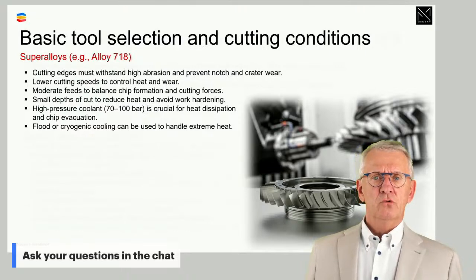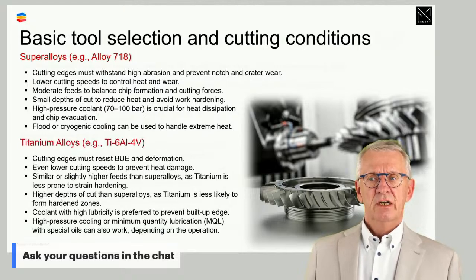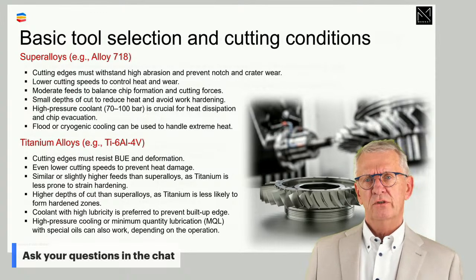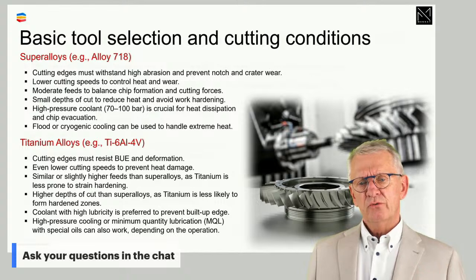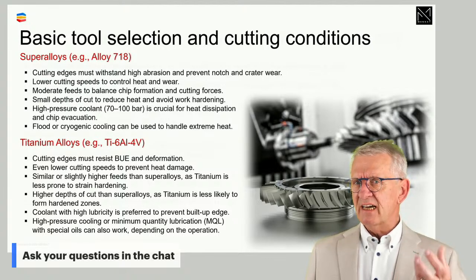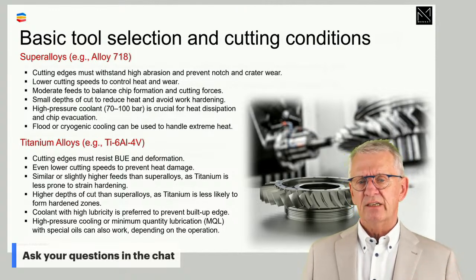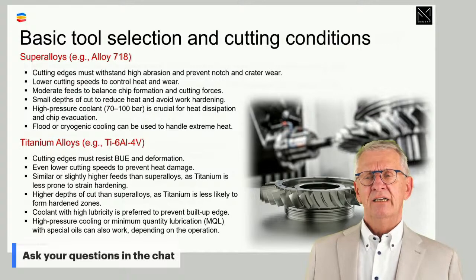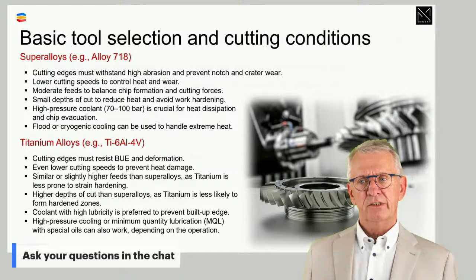When we talk about tool selection, superalloys, we listed the things about tool selection. Titanium is different. Cutting edges in superalloys, they have to have abrasion resistance, notch wear resistance, crater wear resistance. That is important. Where in titanium, it's more about the chemical reaction stuff, the build-up edge thing and so on that we have to be aware of. Superalloys and titanium alloys have in common low cutting speeds. Titanium alloys, it's even lower cutting speeds due to the lower thermal conductivity.